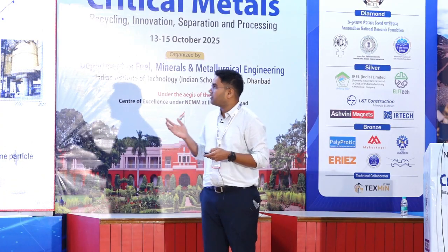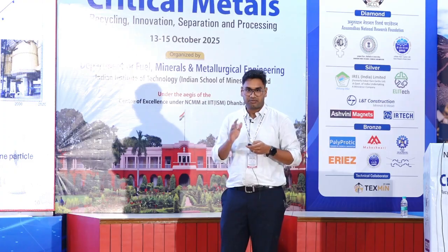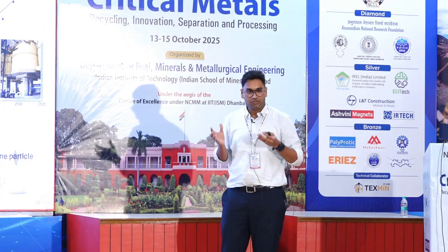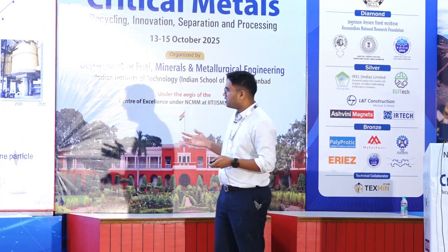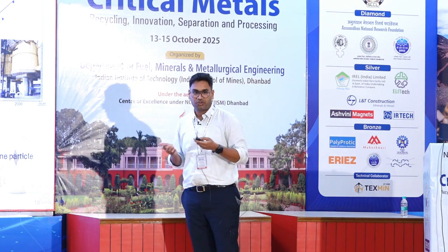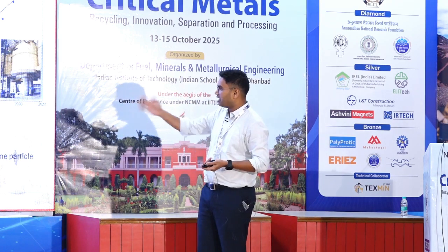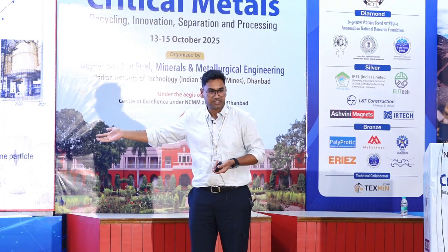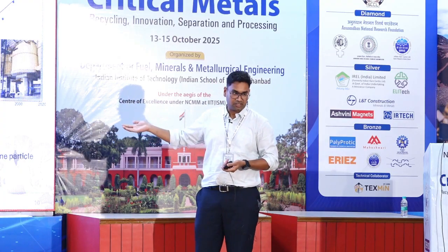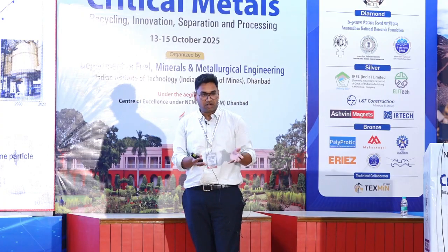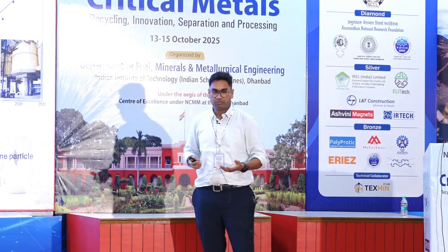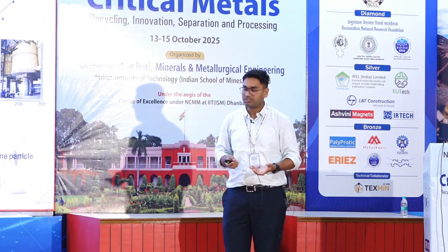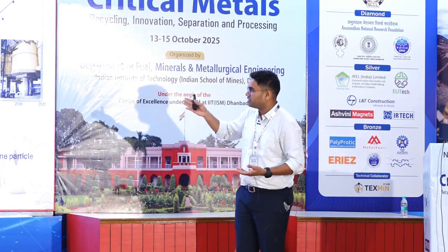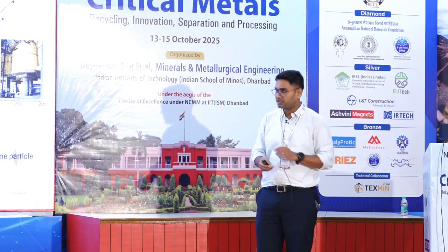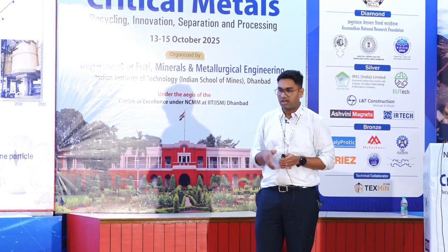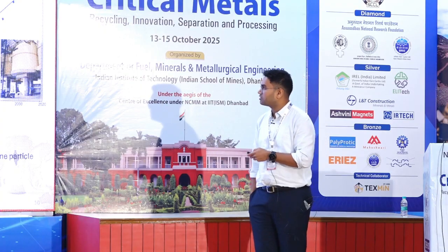So in essence, a large conventional cell can be reduced to a very small cell. For example, a 200 cubic meter cell which was used for a copper flotation can be substituted by a 67 cubic meter stack cell. So you are reducing the size a lot, and you are also improving the recoveries or the extraction efficiencies, because this is targeting just the feed itself, and it's not losing any energy across this cell or the machine.